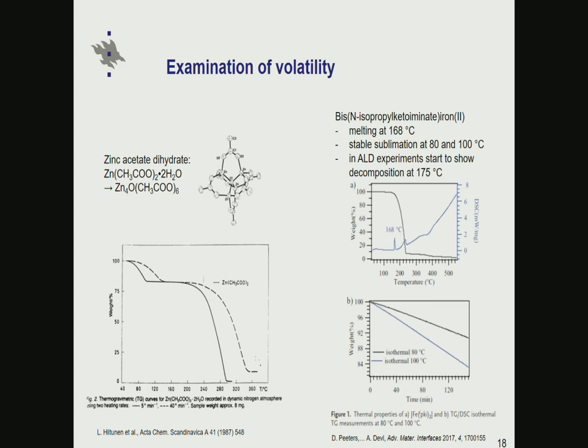That's why there were also some measurements under isothermal conditions, at 80 centigrades and 100 centigrades. In both cases, one sees a linear mass drop as a function of time when this compound is kept at these temperatures. And of course, the mass drop is faster at higher temperatures, which gives an indication and promise that even if the normal TG curve is not completely ideal, one can still use this compound by choosing these temperatures as source temperatures and staying below 175 centigrades. So it's a quite narrow window, but still there is hope to get something done with the precursor anyhow.